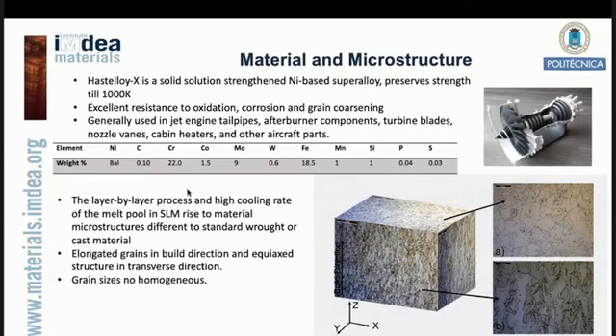Due to the nice weldability and formability of Hastelloy X, and the recent development in additive manufacturing, industry has been using Hastelloy X as an additively manufactured material. But there are some problems, due to the layer by layer process and high cooling rate in the SLM melt pool, which gives a different microstructure that is not similar to wrought and cast materials. Typically, elongated grains are found in the build direction. If you see in the figure here, the first one, A, shows more or less an equiaxed grain structure, but in B it is more or less an elongated grain structure.